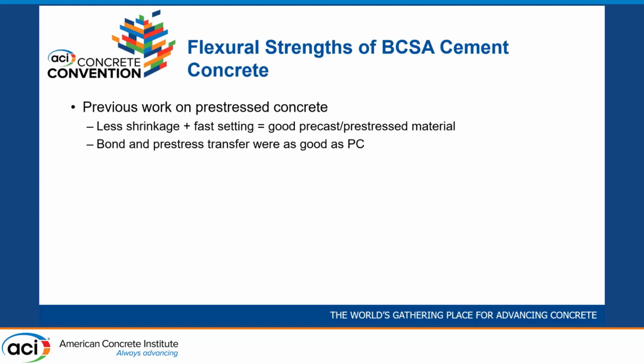So we made a series of beams at OU and tested them. Specifically, we were looking at bond and pre-stress transfer. And we found that it behaved very similarly to Portland cement in terms of those components of its performance.